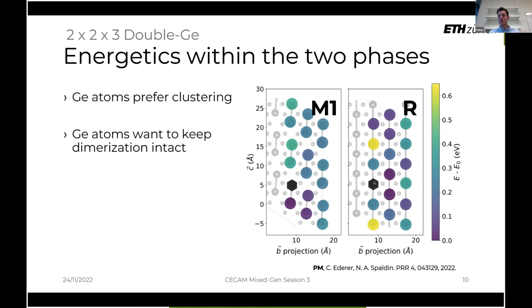But one can also see it in the rutile phase, where the energy of leaving two vanadiums between two germaniums is much lower. If the configuration is such that there is a germanium here and a germanium here, it leaves two vanadiums to nicely dimerize in between, and the system is energetically more favorable. Having a germanium atom here and a germanium atom here with only a single vanadium in between is the highest energy configuration, because it only leaves us with one single vanadium with a single electron in between, which seemingly does not know what to do and hence pushes the energy of this configuration way up.